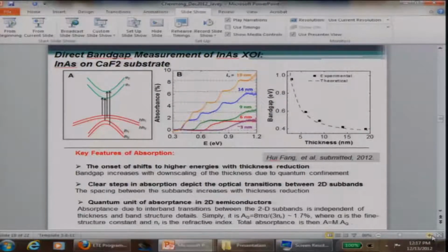As you make your film thinner and thinner, look at this. The band gap shoots up quite drastically. For a 3 nanometer film, the band gap is about 1 electron volt as measured experimentally. So that was the other issue that we had to answer from the beginning: would indium arsenide be good enough? The bulk band gap is too small, and we were always criticized that we were not using InGaAs. We were using pure indium arsenide.